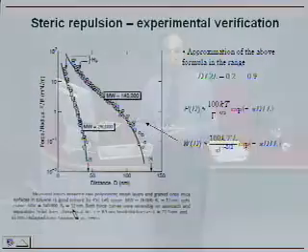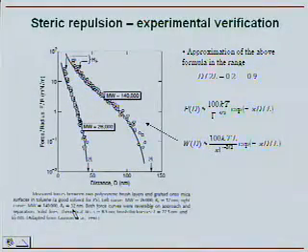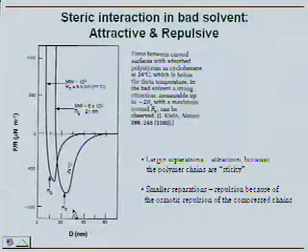But for all practical purposes, just using a large molecular weight non-ionic surfactant stabilizes your particles well enough if it adsorbs. So if you want to engineer repulsive interactions, and you want to make sure that they stay repulsive, you put in steric stabilization. And one final slide about this.